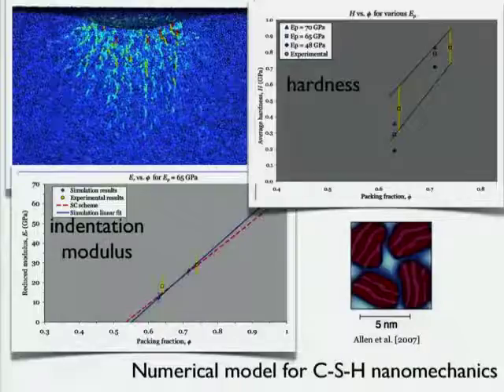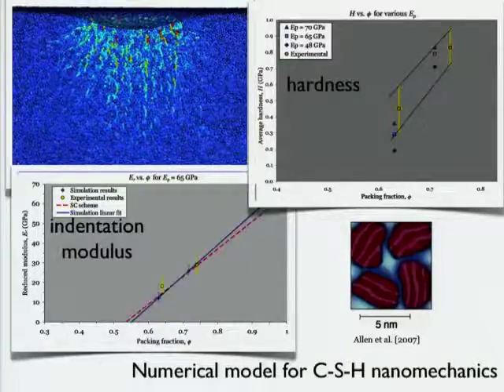So here's the tip of a nanoindenter pushing down on a sample of cement. And what you see here in color are stress chains, right? So you're clearly stressing the area around the tip of the indenter. Now, this exact same experiment was conducted at MIT physically. Okay, there was a physical experiment. And so the yellow points here are the results of a physical experiment.